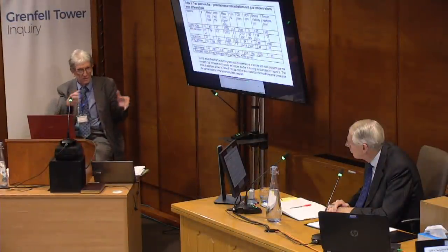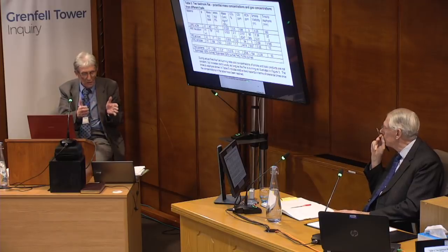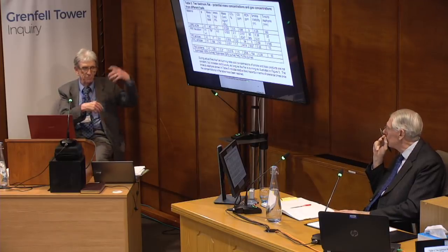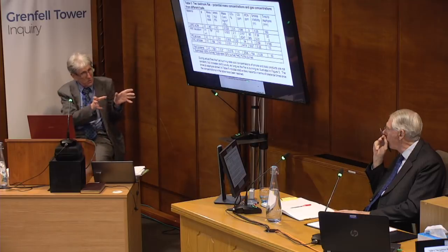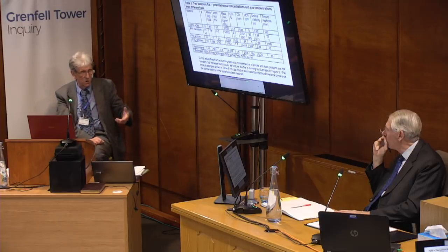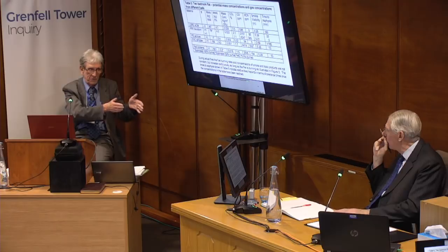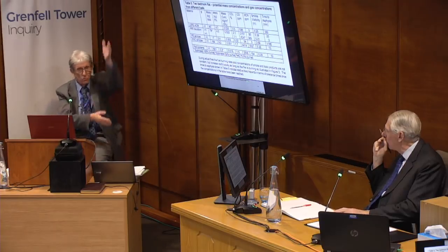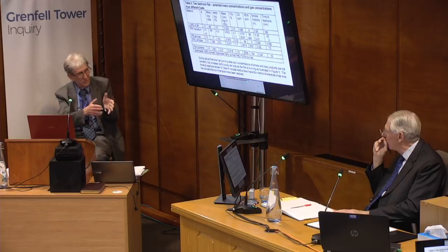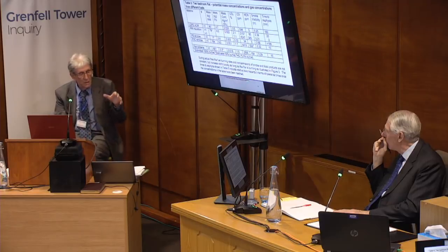What I looked at was the thickness. And for this kind of indicative calculation, and I'm thinking mainly of the spandrels here, but that's the same logic I've applied to the other, you've got two aluminium-faced layers. So if one of those layers is gone, and that's what I observed appeared to have happened, then that's 50% of your PIR gone. So I've assumed all that's combusted, right? But behind that is the layer that the windows are set in, which is still attached in places to the concrete of the building. And that is all blackened and charred and sort of bulbous.